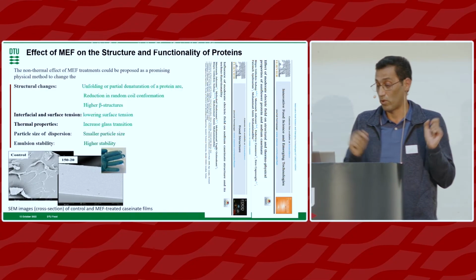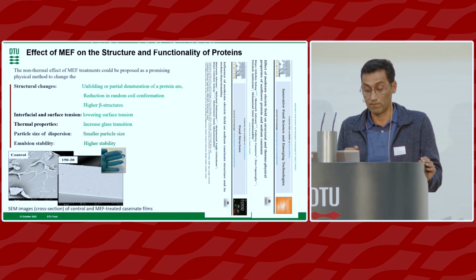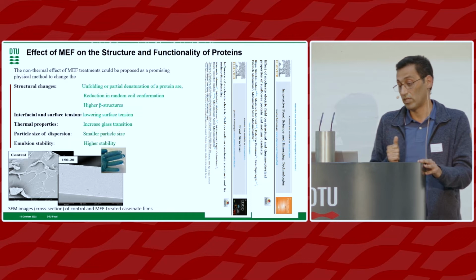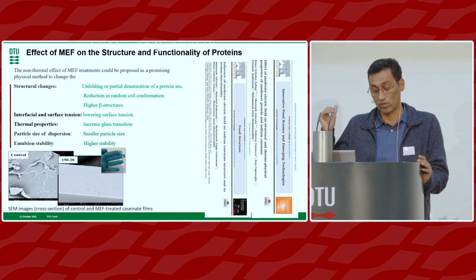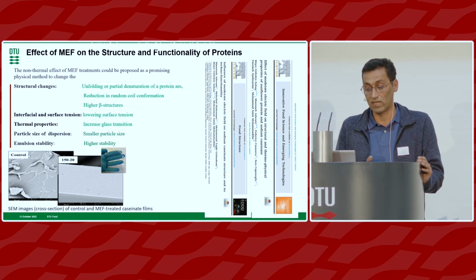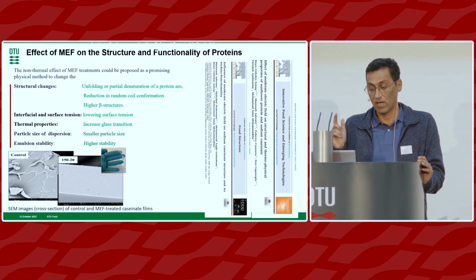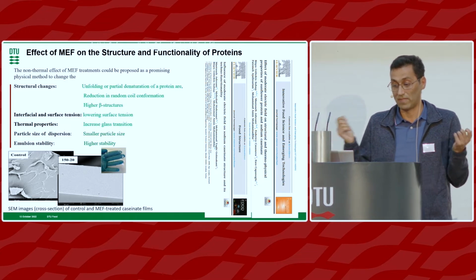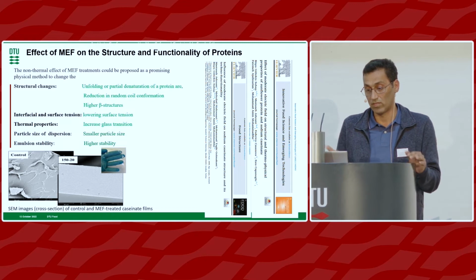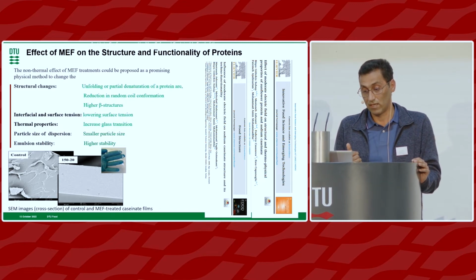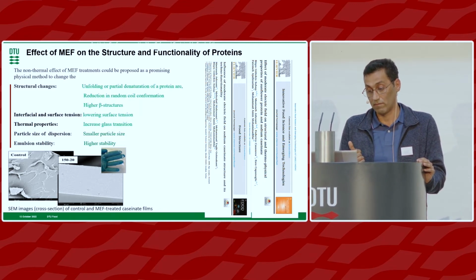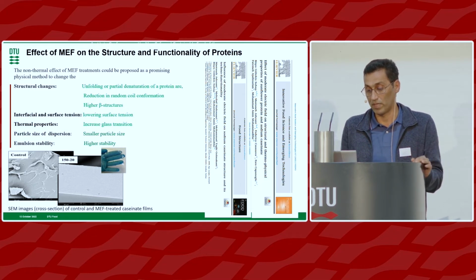I know that there are some projects between KU and Arla about this. And then we used these electric field treated samples to stabilize emulsion, and then we ended up with high stability. So that means the hydrophobicity has been changed also, which we expected to have because of the opening of the structure.